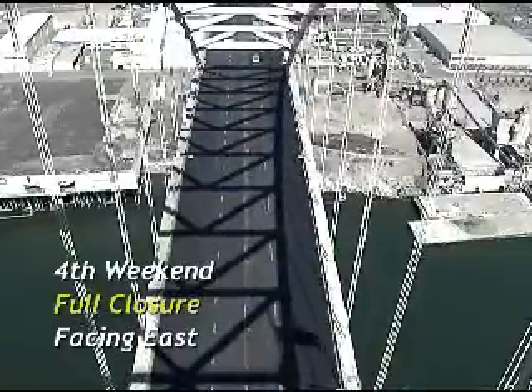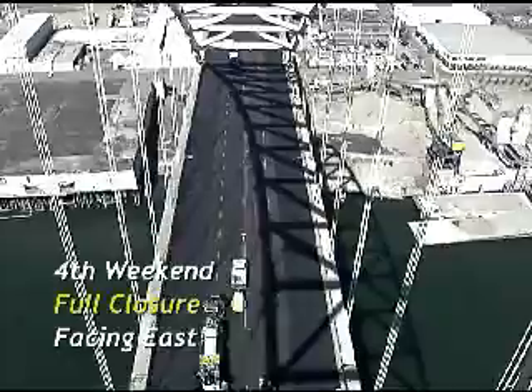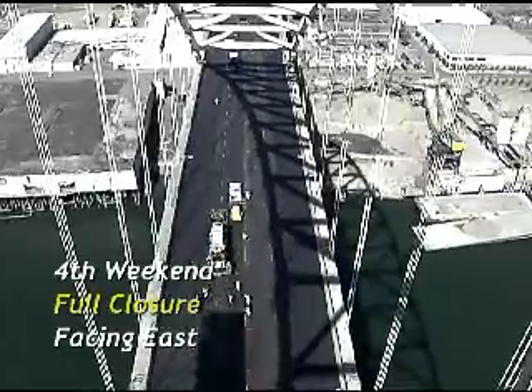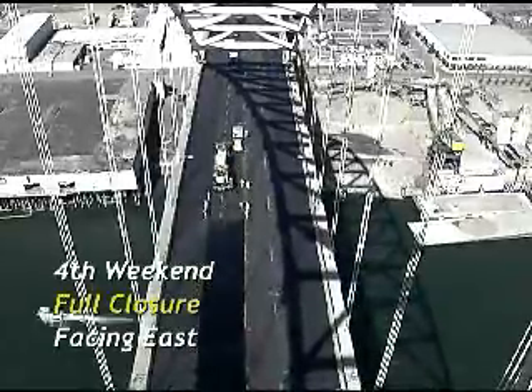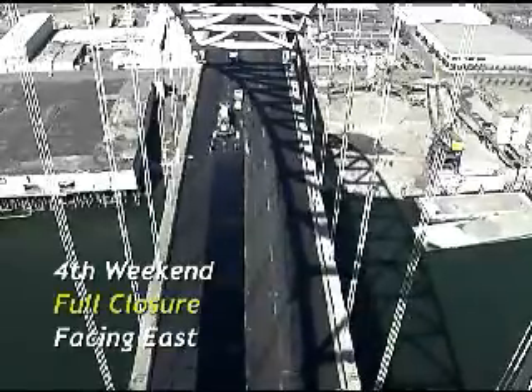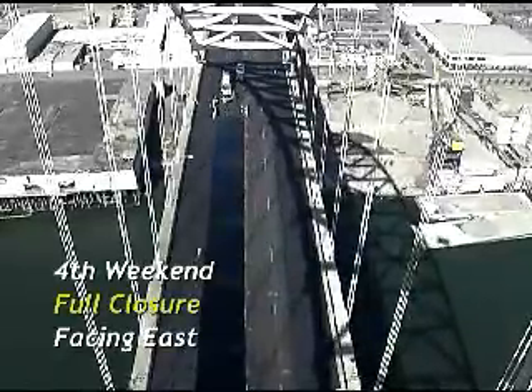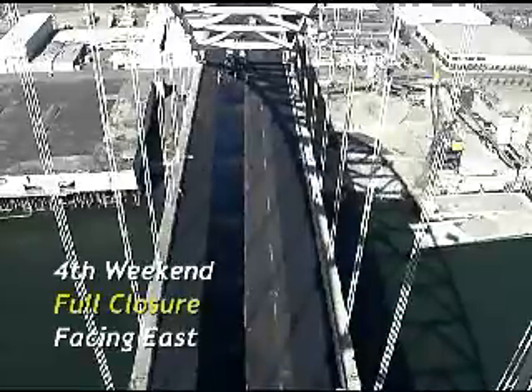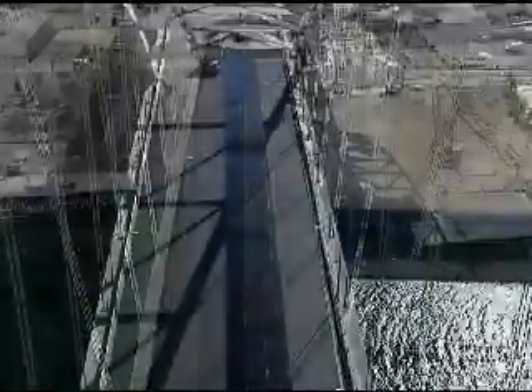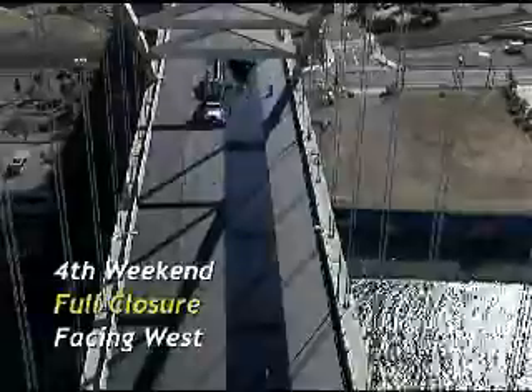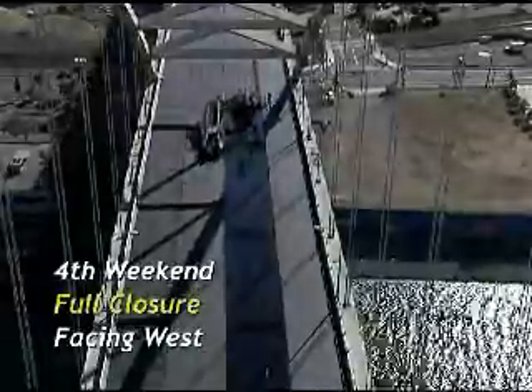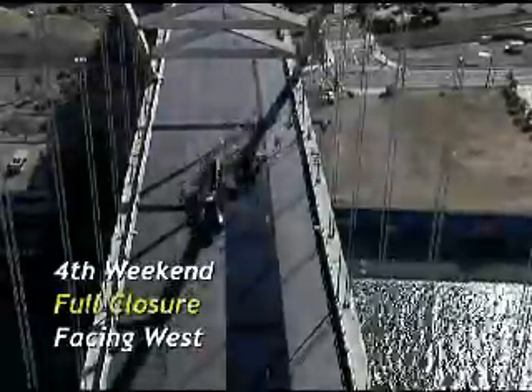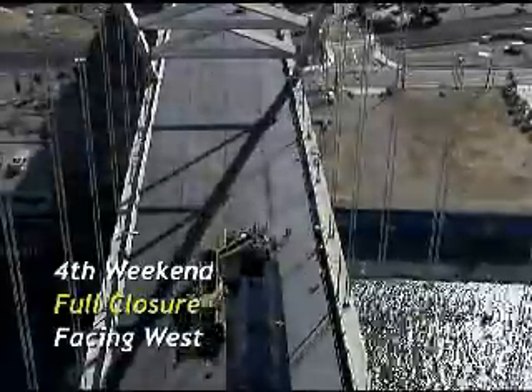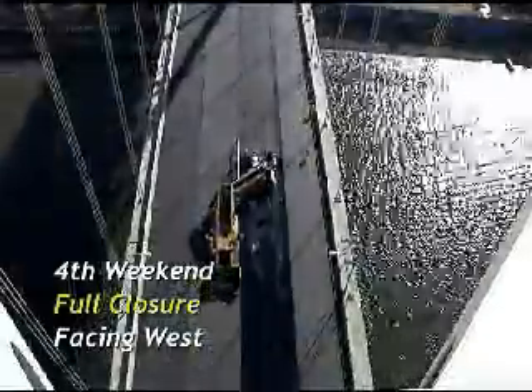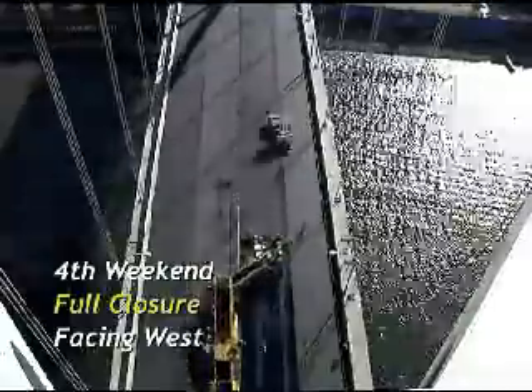After the asphalt's produced and placed in trucks, they insert long stem thermometers in the side of the truck. So as the truck travels to the bridge site, those thermometers start reading the temperature of the mix inside. Once it arrives at the bridge site, we monitor the readings on those 3 thermometers, average them out to get a single reading, and that determines how long that load of asphalt needs to set. If the truck doesn't dump its load within that window, the asphalt will lose its workability to be able to be placed and compacted, so that truckload will get rejected.